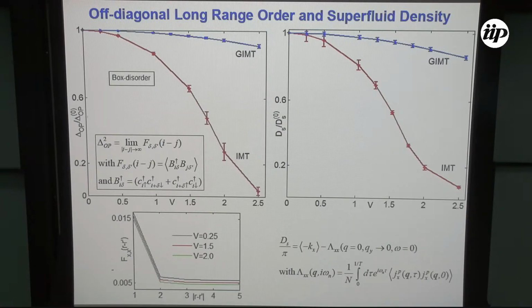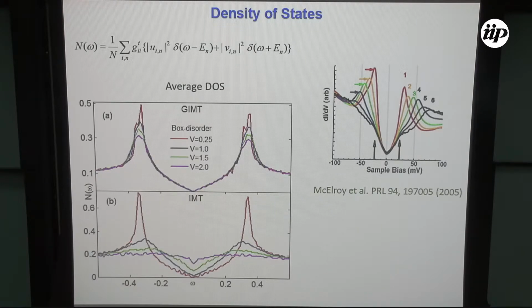So what happens in the density of states? Let's look at it. If we look at a normal d-wave superconductor, it's like this V-shaped density of states. If we introduce disorder with no strong correlation in the lower panel, you will see that as you increase disorder strength, it will be flat with no coherence peak, no superconductivity, and no gap. The mid-gap states would be completely filled up. If you include strong correlation, even for this flat density of states without strong correlation, if you include that in GIMT, it would be robust at low energies. It is very similar to what we saw in experiments, that the low energy density of states would be robust to impurities.